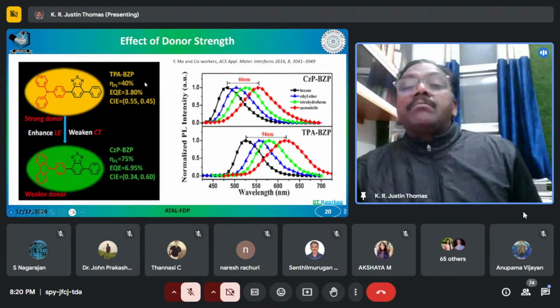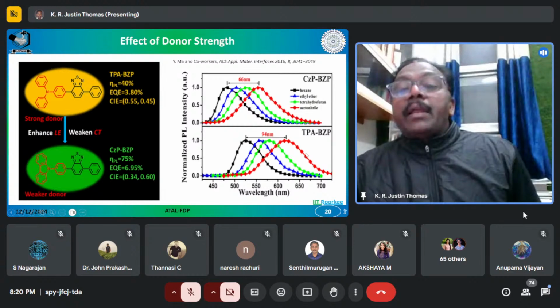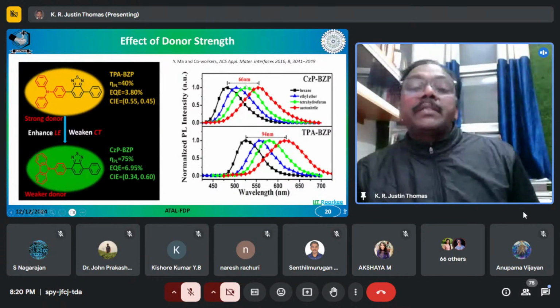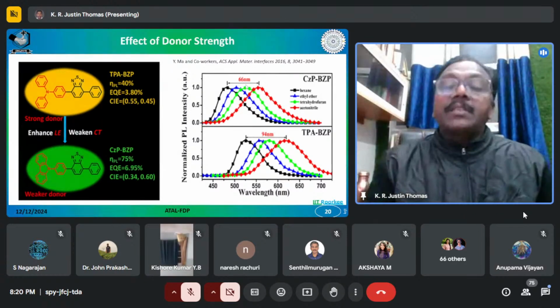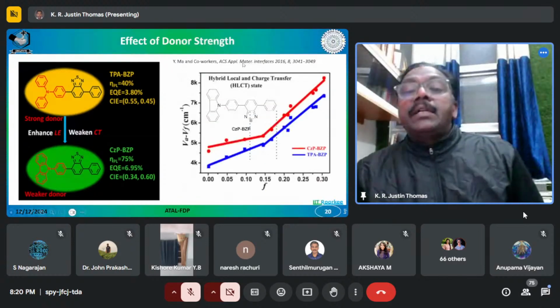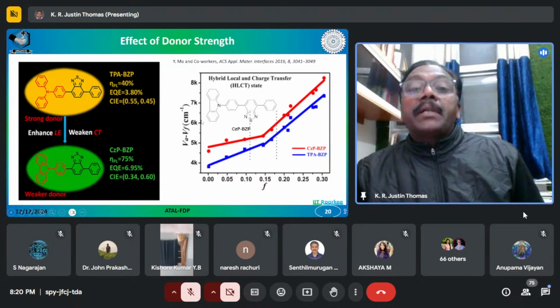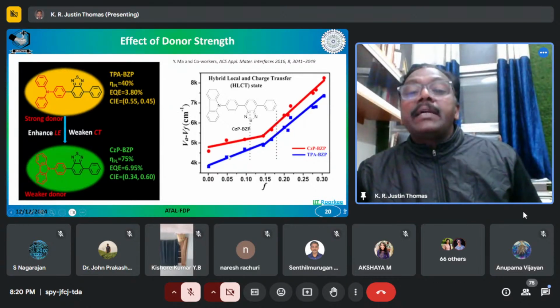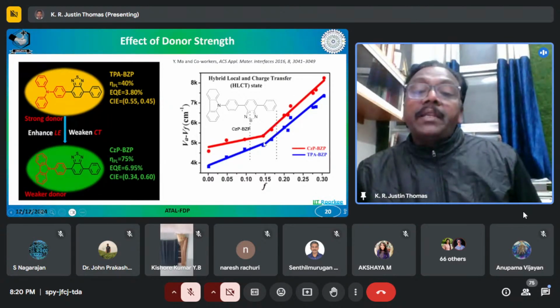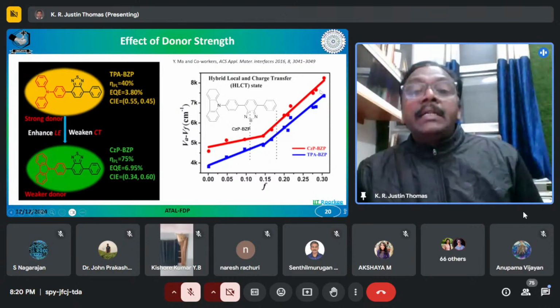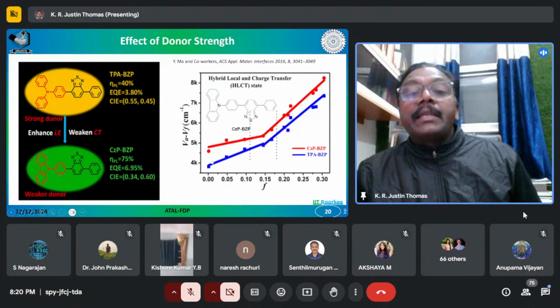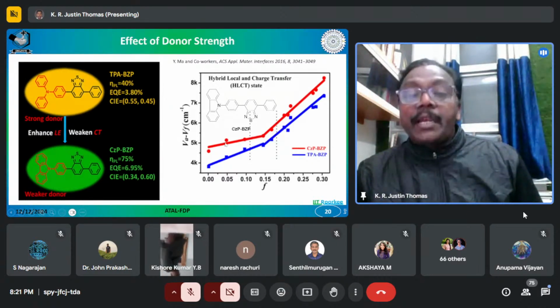And the strong donor triphenylamine leads to a huge solvatochromic shift of 94 nanometers. However, the carbazole leads to a small solvatochromic shift of 66 nanometers. So that again shows that the donor strength variation has a huge effect on the emission characteristics. And then the last one is that when you plot a Lippert-Mataga plot, where you plot the orientation polarizability of the solvent against the Stokes shift, you normally expect one straight line relationship, but here you are seeing a two straight line relationship. That means the molecule is not showing any variation in the Stokes shift in nonpolar solvents and shows a huge variation in the Stokes shift when the solvent polarity is increased. So that leads to two slopes, a two straight line relationship.